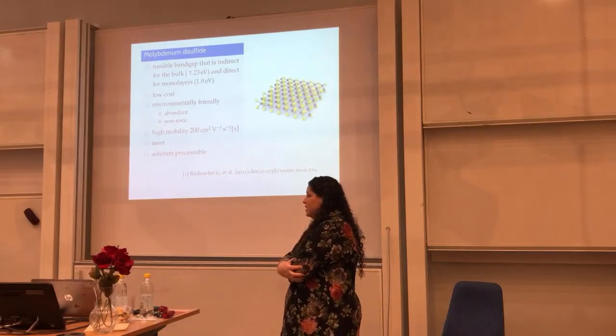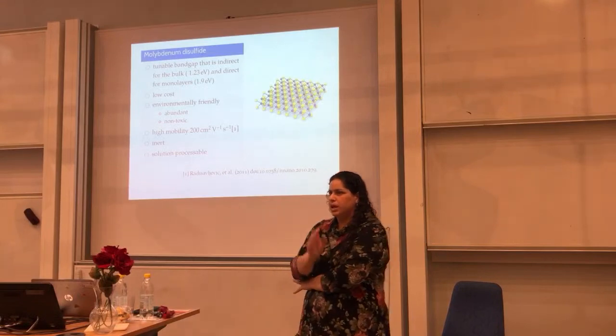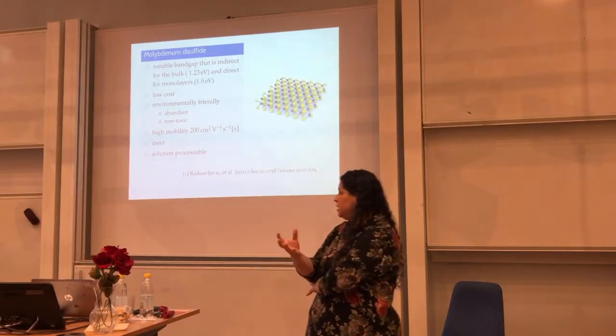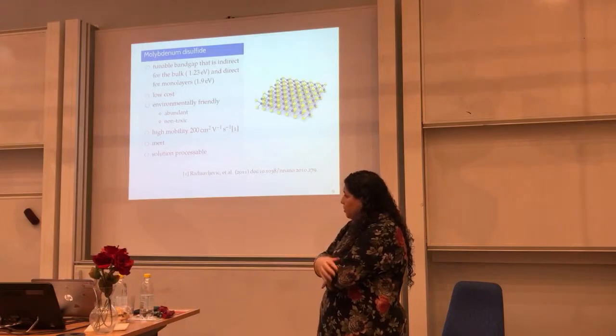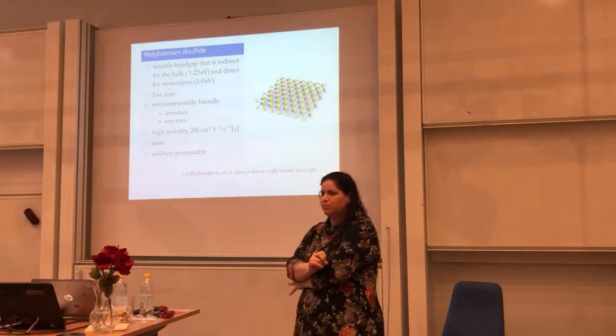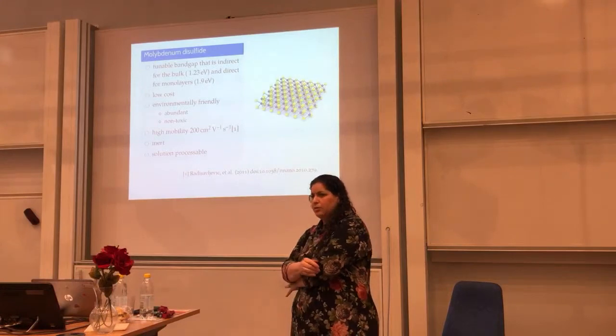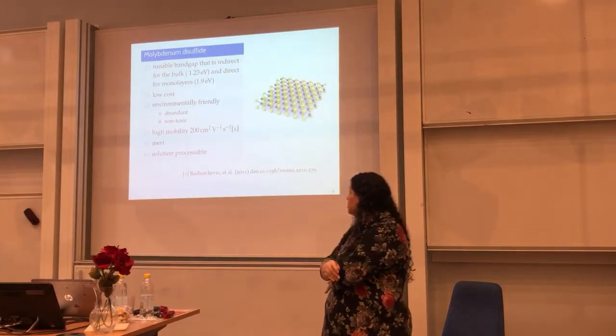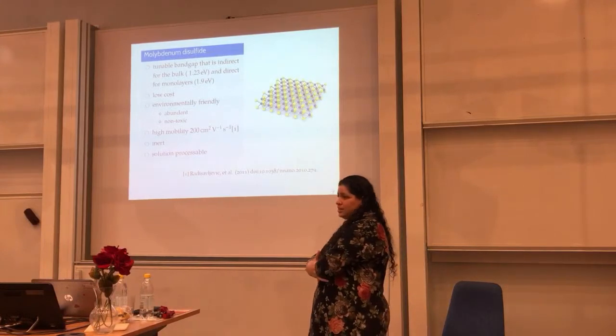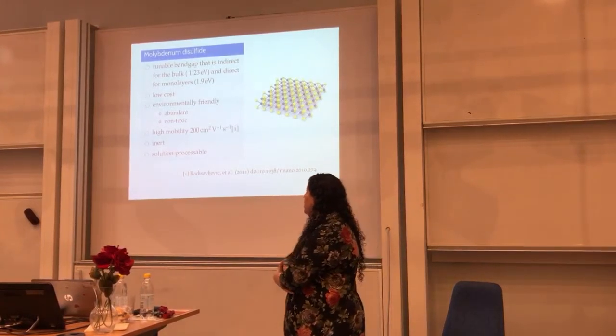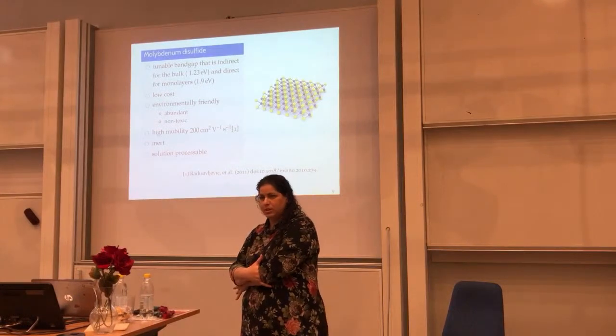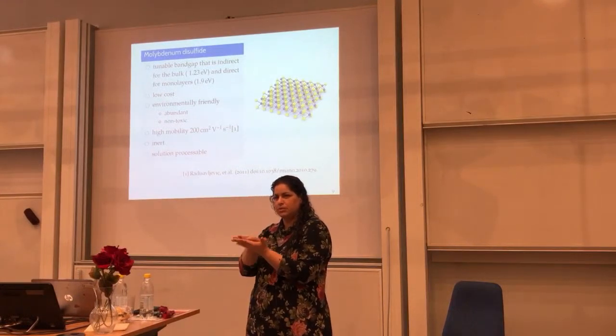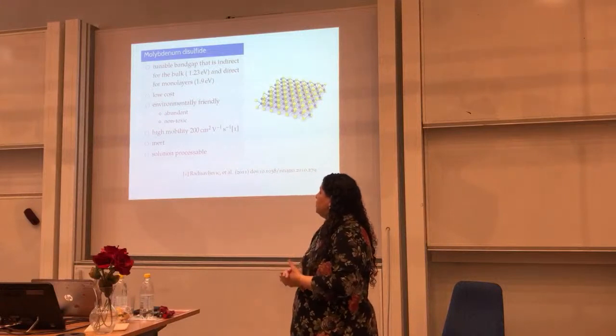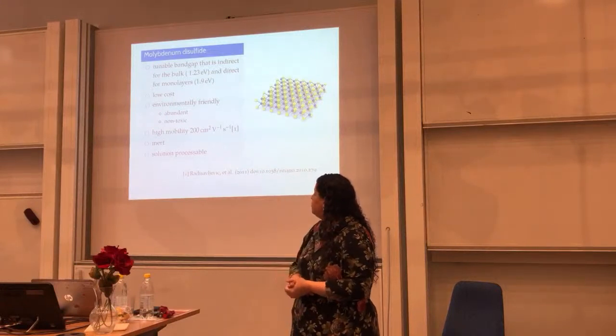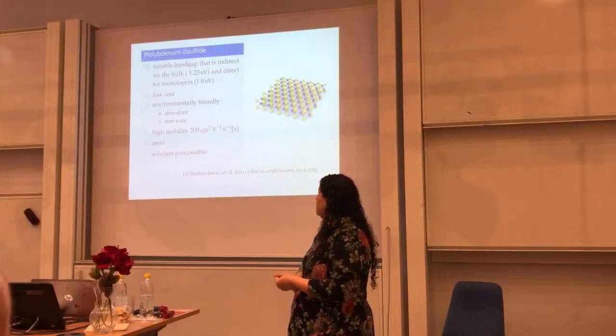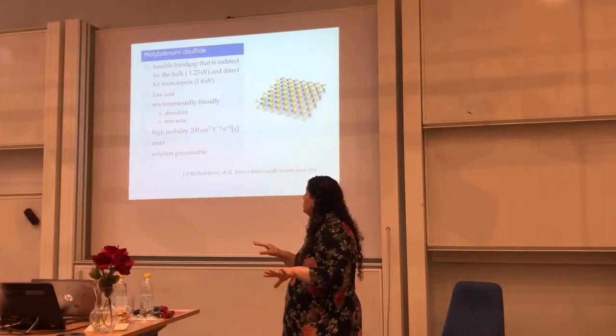Then there was a need to find other materials that could also be used like graphene in the nanoscale world, but that have the properties that graphene lacks. And what are the properties that graphene lacks? One of the most important properties that graphene lacks is a band gap. And if you don't have a band gap, you cannot use it in transistors, because you cannot switch on and off this device built out of it. So that's where molybdenum sulfide comes into place. Molybdenum sulfide will have a tunable band gap. What does it mean?